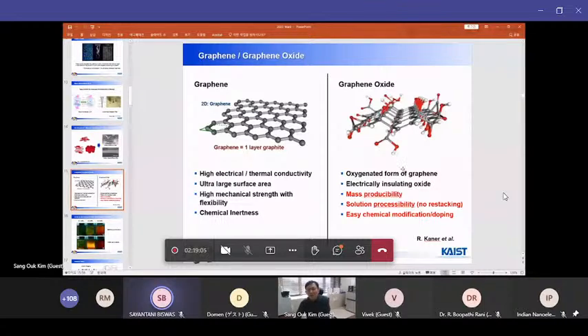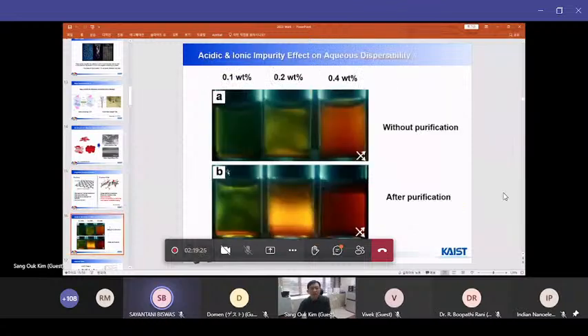And other than that, those oxidized functional groups can be further exploited for nitrogen doping or any other chemical modification. Actually, graphene oxide research was initially introduced by Professor Rodney Ruoff, but if you simply follow the well-known Hummers' method, then you will see solid precipitation of graphene oxide even at such a low concentration. But we found that this is due to the impurity effect. After our careful purification, we could see some precipitation again, but it is not a solid precipitation anymore, but an interesting liquid crystalline state.